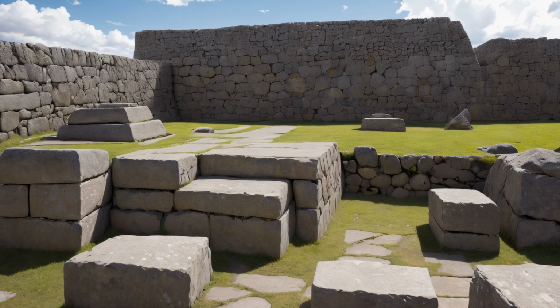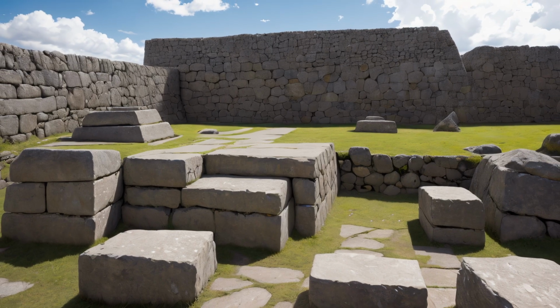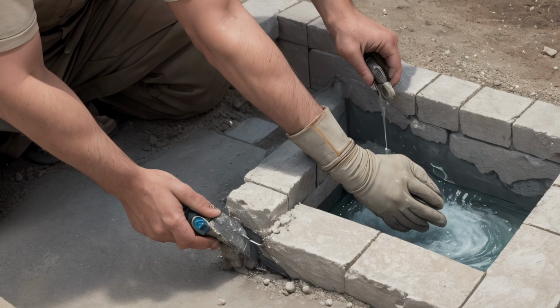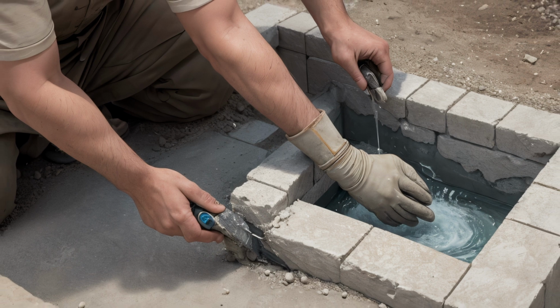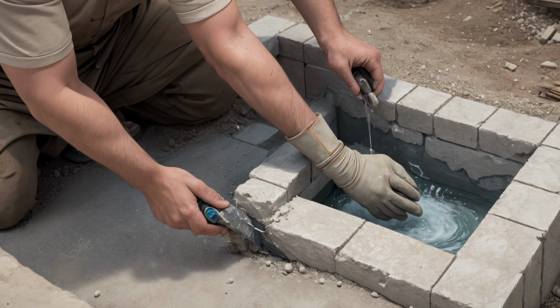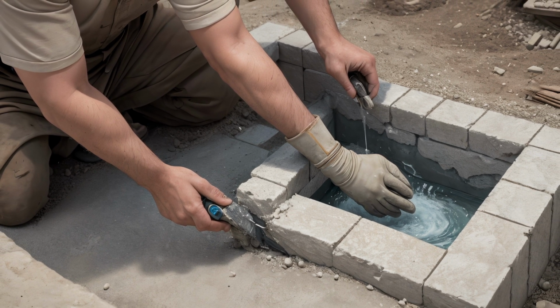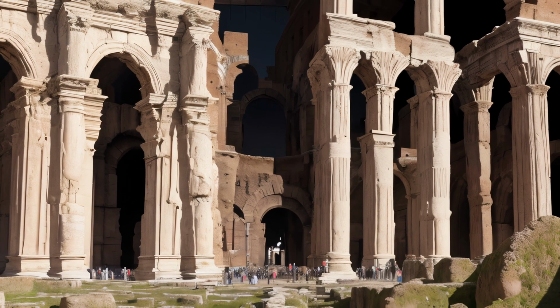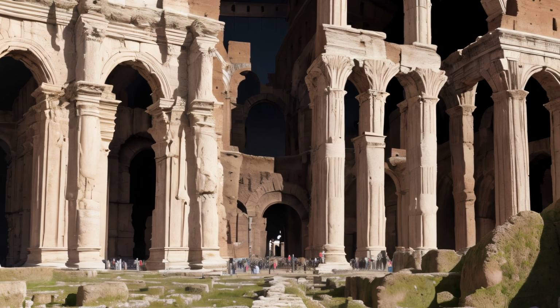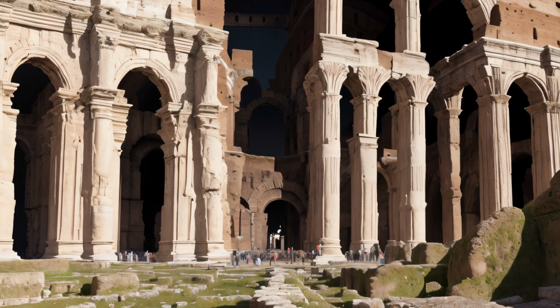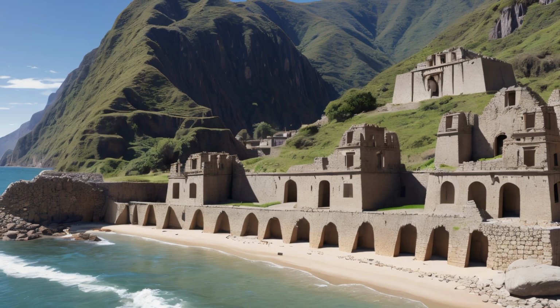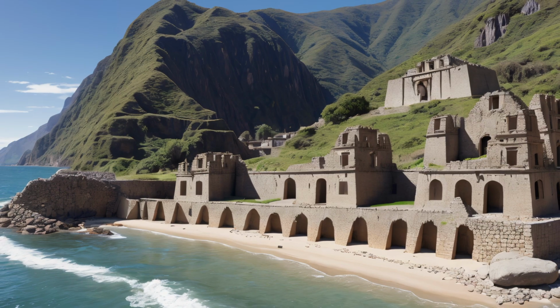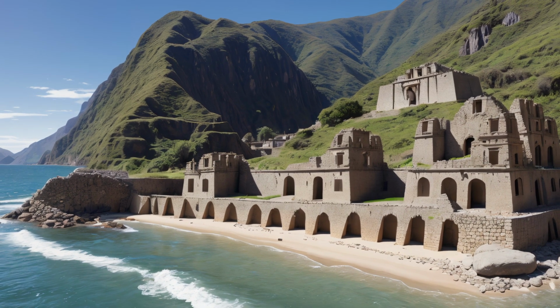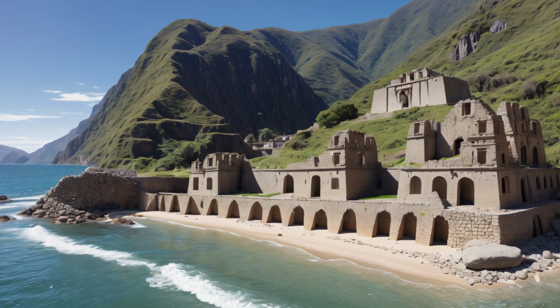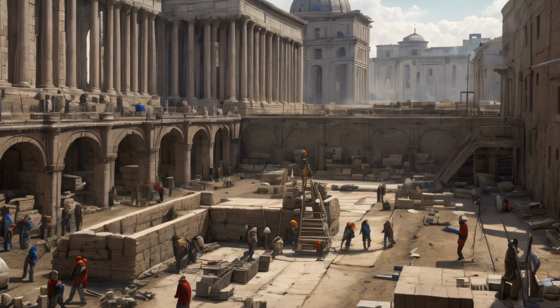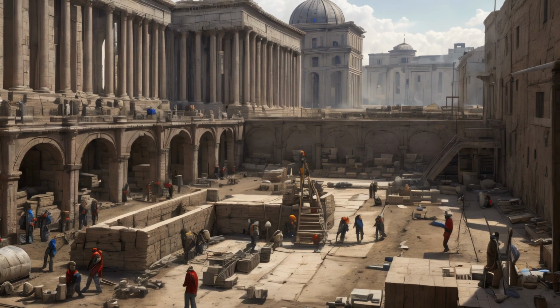This process, known as pozzolanic reaction, not only filled voids within concrete, but also created a cohesive bond between aggregate materials, enabling structures like the Pantheon's dome and the Colosseum's foundations to withstand centuries of ground movement. The grout acted as a continuous medium, distributing shear forces evenly across joints and preventing localized cracking that could lead to catastrophic failure. In contrast, the Inca Empire achieved similar stress distribution through mechanical interlocking rather than chemical bonding.